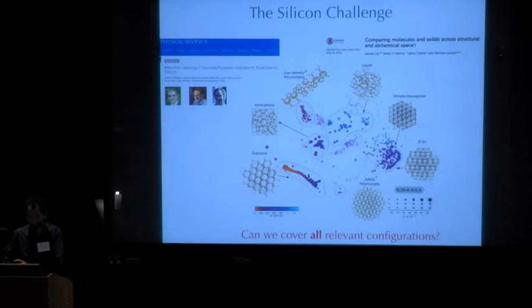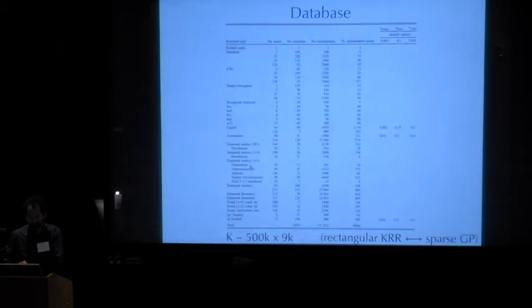Okay, let me illustrate that on the silicon. This is a database, and look at the number of atoms in each of the calculations. They are about order 100. So these are small unit cells that represent the local environments that we might encounter in a big simulation. And then we take that database, we regress it, and then we do a 1,000,000 atom simulation where all the local environments are hopefully represented, and we do this atomic convolution.